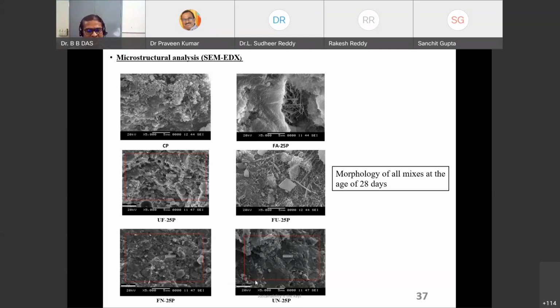That means you have a dense microstructure when you add nanoparticles to the cement system. Here, you don't have a dense microstructure. You can see the fly ash, a lot of appendices, a lot of wires. That indicates a loose microstructure. But we cannot really quantify this. This is basically our morphological observation.